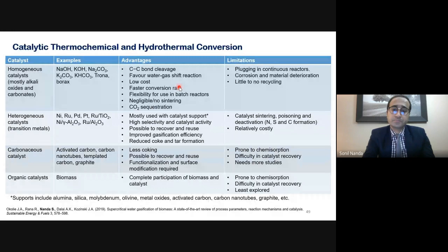For example, they lead to carbon-carbon bond cleavage, they lead to a better water-gas shift reaction in hydrothermal conversion, faster conversion rates, flexibility for use in different batch reactors, negligible or no sintering, and there is a possibility of carbon dioxide sequestration in the form of carbonates that are formed in the hydrothermal conversion. However, there are some limitations, such as plugging in continuous reactors. Corrosion and material deterioration is also one of the major limitations. And one of the major bottlenecks is that these homogeneous catalysts can rarely be recycled or recaptured after the gasification. They will mostly end up in the products or the solid residues.